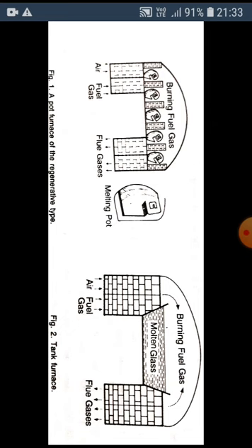In such type of furnaces, the walls of the tank serve both to restrict and retain the heat and to hold the glass. The batch is mixed with cullet because it assists in lowering the melting point, and the pot or the tank furnace is filled to the desired height. The tank is heated to about 1400 degrees centigrade, at which the materials melt and react to form molten glass.